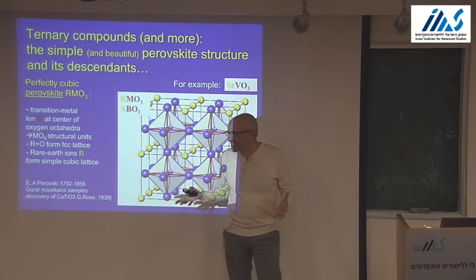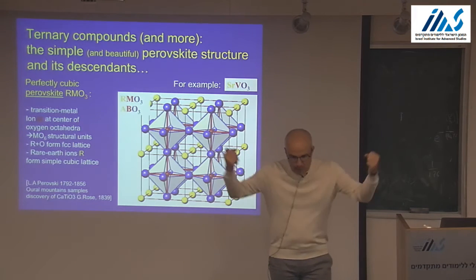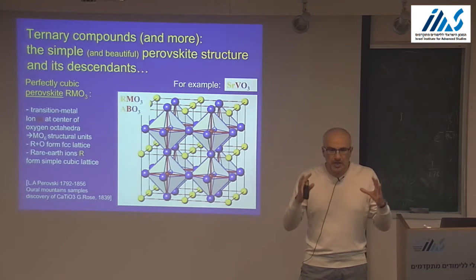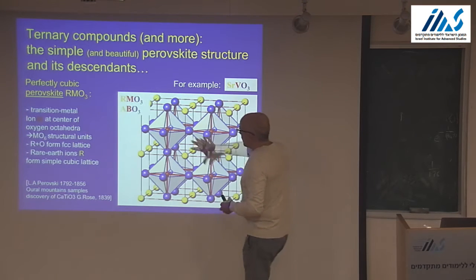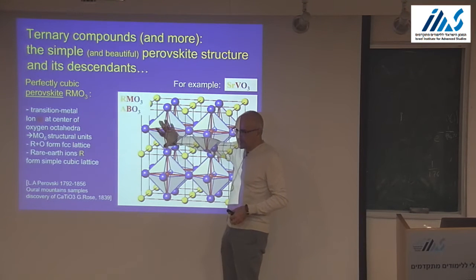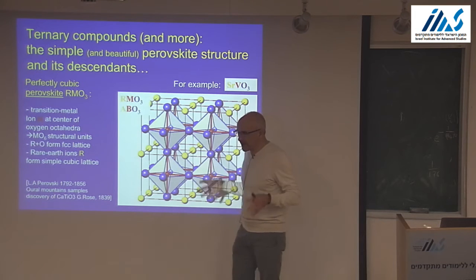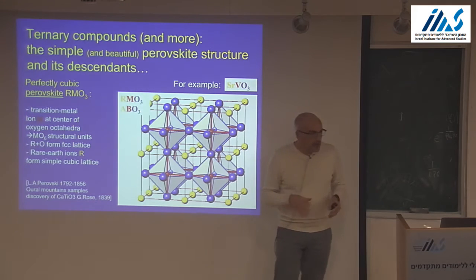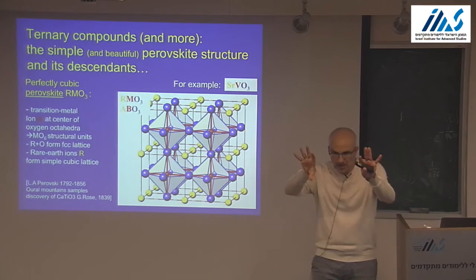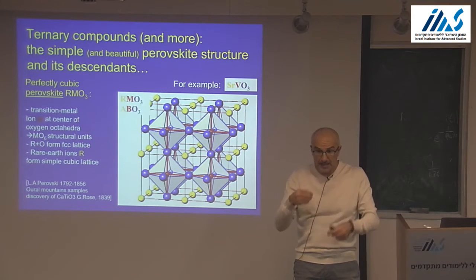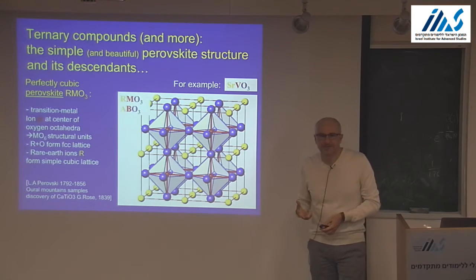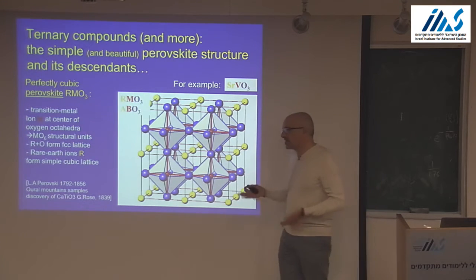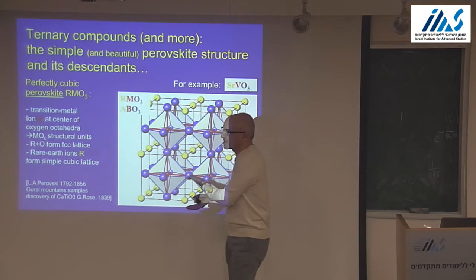So you increase the nuclear charge, Z, and hence the electrons get pulled in more strongly, and hence the ionic radius goes down. As we go to smaller and smaller rare earths, we have more room for these guys to actually tilt and rotate. And so when you have a big rare earth, like strontium or lanthanum, this structure actually likes to be close to cubic. But when we move to heavier rare earths, typically these things tilt and rotate. And that's another control parameter of these structures, besides the doping. So is it the rigidity of the structure? Well, I mean, it's a compromise between electrostatics and bond formation.